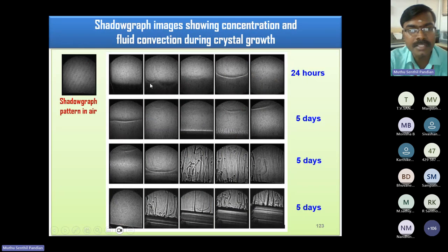You see, the concentration at the bottom portion is very high compared to the top portion. After 11 days, the plumes start from the bottom of the glass sample. The plume is nothing but the movement of fluid flow from high concentration to low concentration. The crystal started growing at its 12 days time.